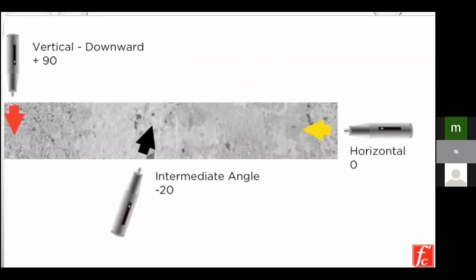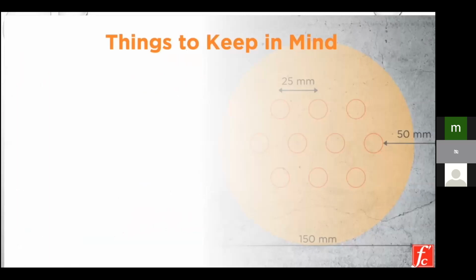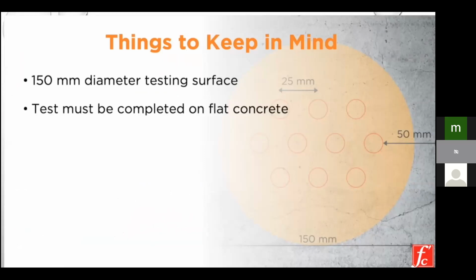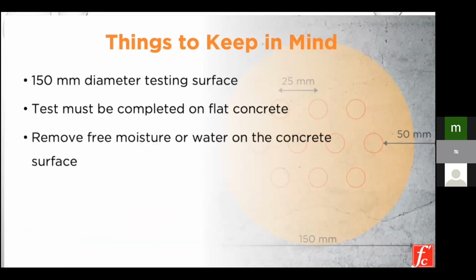Inspectors should pay attention to the following considerations prior to conducting a rebound hammer test. The testing surface should be at least 150 millimeters in diameter. The surface should also always be smooth before testing. If there is any free moisture or water on the concrete surface, it must be removed.